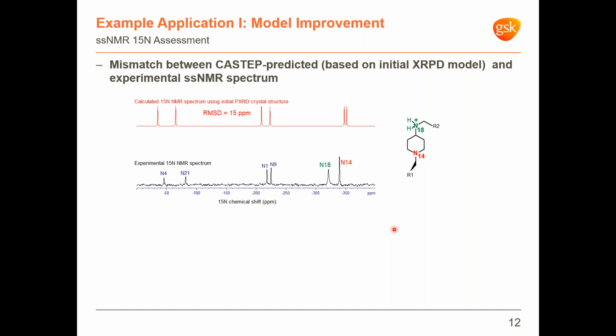Beyond statistics of the solid-state carbon-13 data, the solid-state NMR of nitrogen-15 clearly describes the actual improvement of the structural model in terms of features of the molecule mostly affected and improved by the CASTEP optimization. The top spectrum in red is based on the CASTEP calculated chemical shieldings on the initial model from XRPD structure solution and Rietveld refinement. Comparing it with the solid-state experimental pattern in black at the bottom, we see some discrepancies, especially for nitrogen-14 and nitrogen-18, highlighted in this detail of the parent API molecular structure. Overall, RMSD for spectrum comparison is 15 ppm.